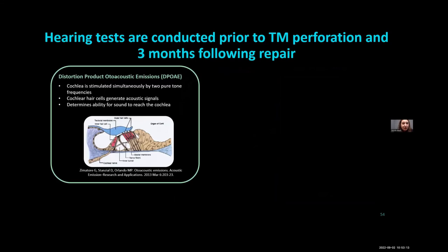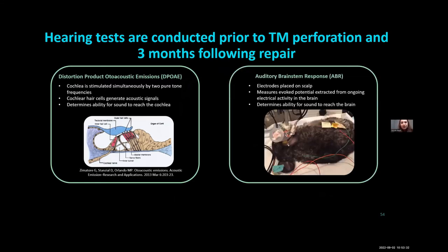The other thing, a functional test for efficacy testing that we're performing, is hearing testing. There's two main hearing tests, since you can't ask the chinchillas if they can hear. One is called distortion product otoacoustic emissions, or DPOAE, where you're essentially trying to figure out if sound reaches the cochlea. The other one is auditory brainstem response, and this is a test they commonly do on babies, where you see if the sound waves reach the brain. In both cases, you'll play a single frequency louder and louder until either you can detect these otoacoustic emissions in your cochlea for the case of DPOAE, or you can detect brain waves in the case of ABR. When you can detect these, this is noted as a threshold.